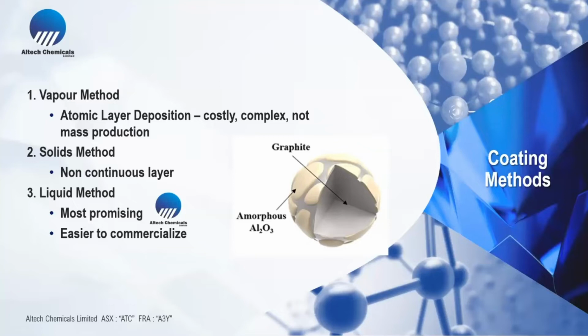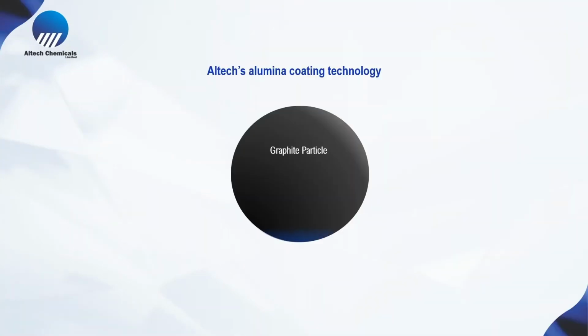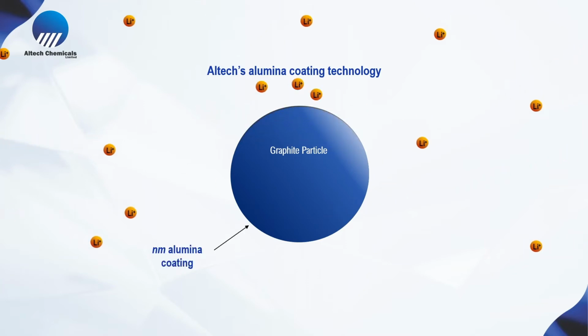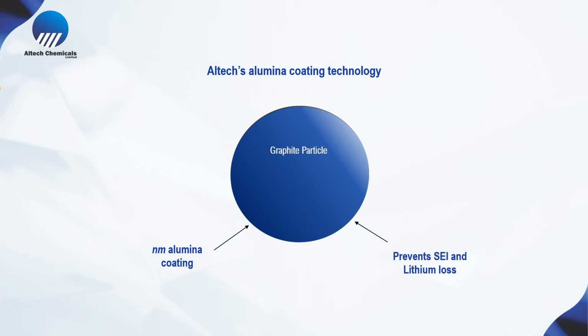Now, there are 3 ways of coating alumina onto graphite: the vapor method, solid method, and the liquid method. The vapor method is atomic layer deposition, but it's very costly, complex, and doesn't lead to mass production. We're focused on the liquid method, and it's really the most promising and easy to commercialize method. Essentially, we coat a graphite particle with a fine layer of alumina, and the alumina layer stops the lithium from forming on the graphite material.